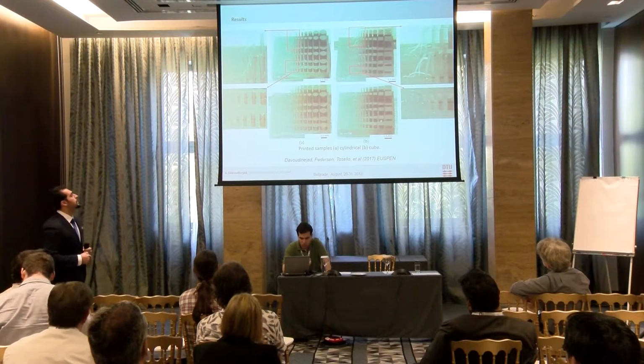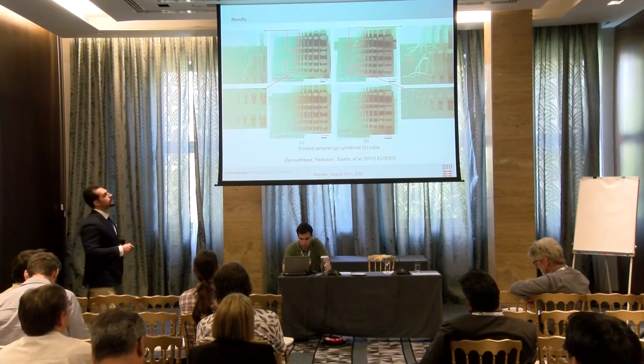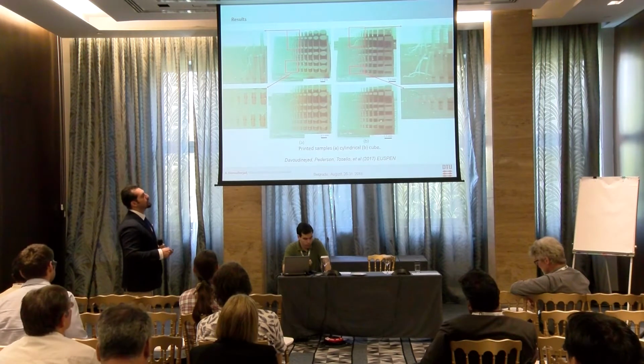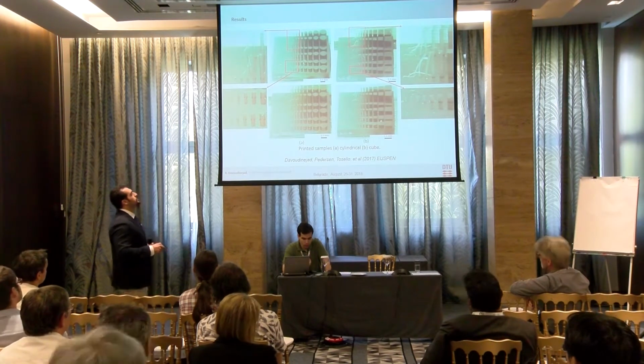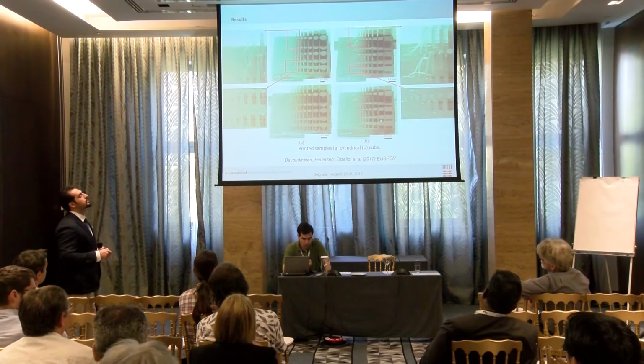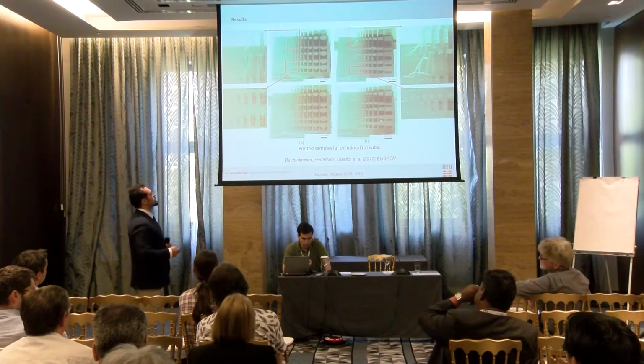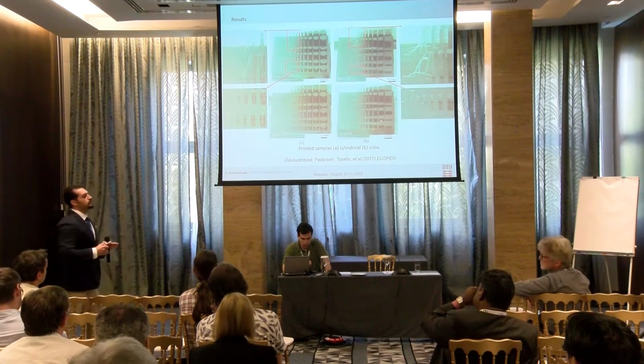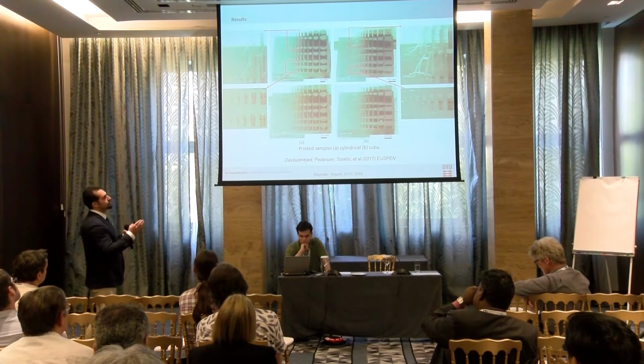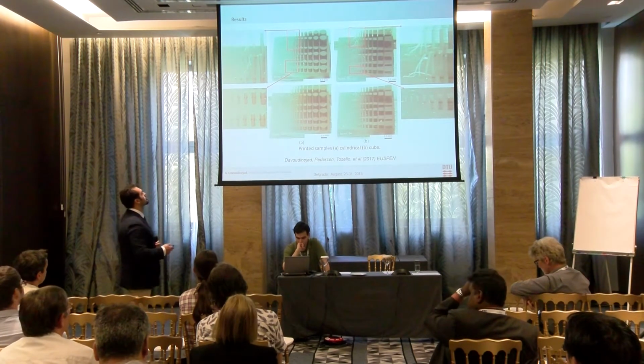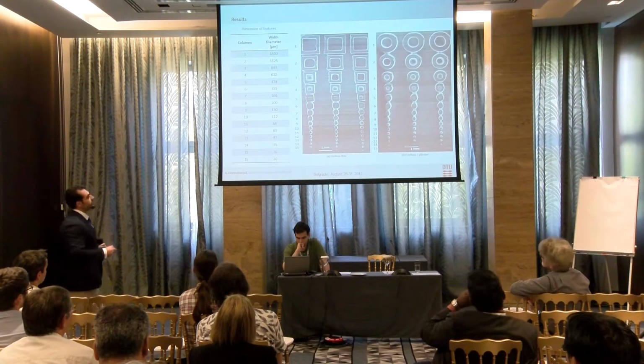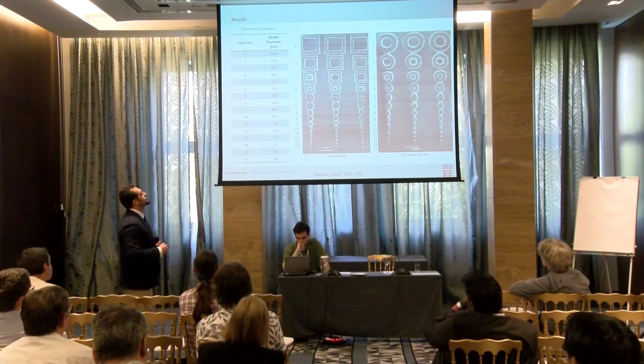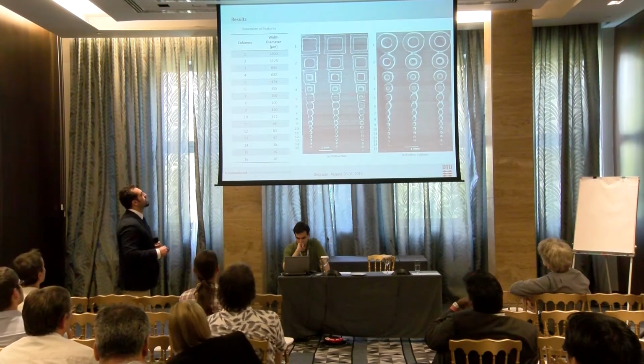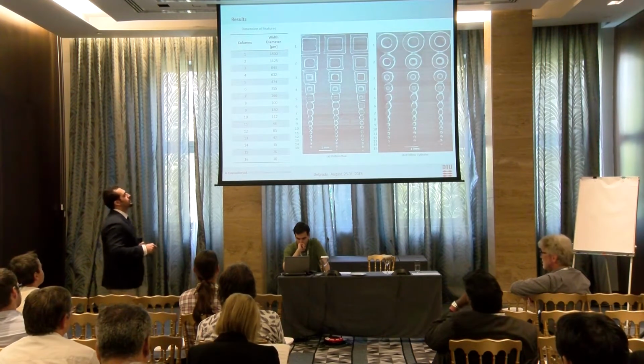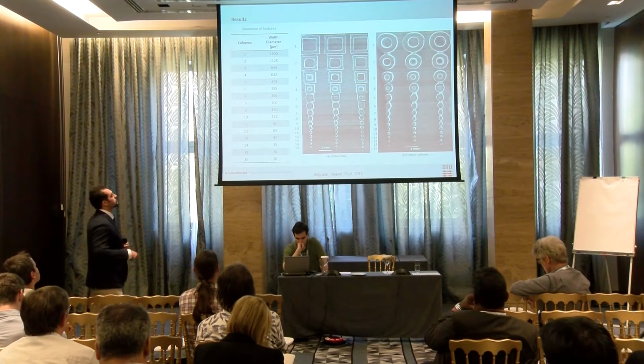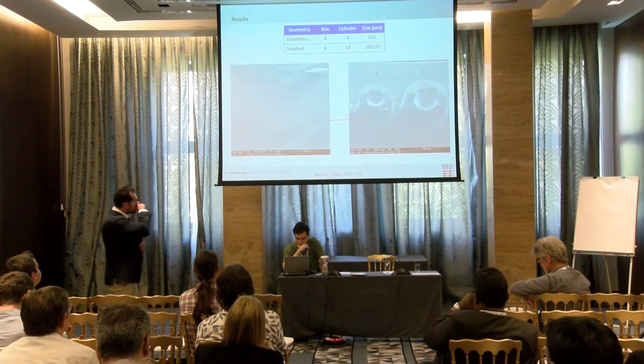The other problem that we have is the high aspect ratio feature, which has a failure. As you can see here, at 500 micron height, the features are printed quite well, but at 2 millimeter height, they start to bend, and we have failure in the high aspect ratio features. This is also because we push the post-processing a bit, and it affects these tiny pillars. This is the main result from the SLA, which we can see up to the fourth column. We have the hollow square and hollow cylinder, and the rest is all filled with resin, and we cannot go beyond that.